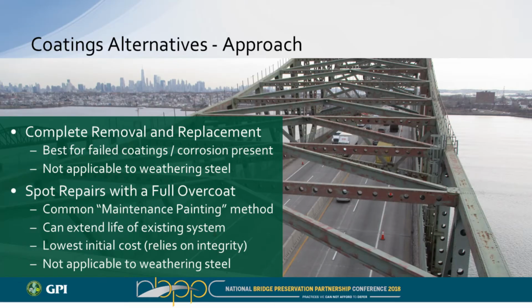So if the underlying coating system, the original coating systems, are brittle, or if they're pulling off, as soon as you put that new system on, it's going to pull that stuff off the substrate as part of the curing process. You could actually accelerate the failure by going through this overcoating. And again, not really applicable to weathering steel structures, as there's no independent coating.